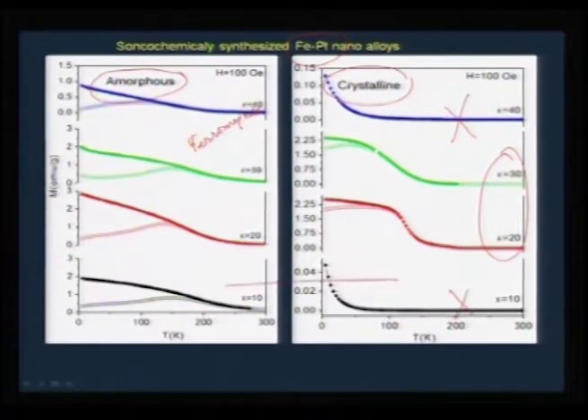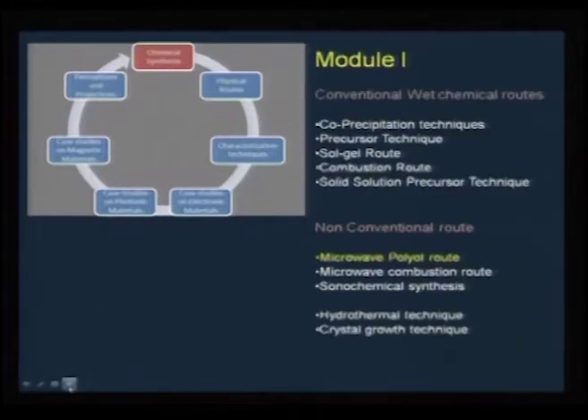Therefore, if you try to compare with the as-prepared compounds, even those compositions which are supposed to be showing an order-disorder parameter, where it is not supposed to be magnetic, turn out to be magnetic in nanophase, and this is possible through the sonochemical approach.